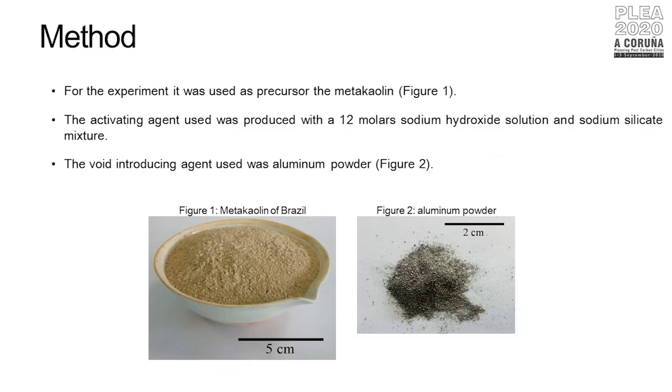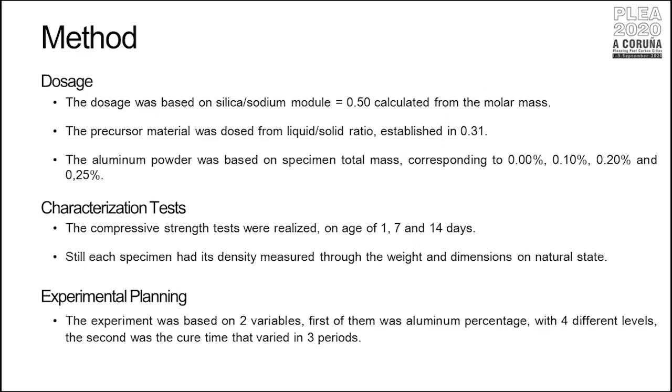For the experiment, metakaolin was used as precursor. The activating agent used was produced with a 12 molar sodium hydroxide solution and sodium silicate mixture. The void introducing agent used was aluminum powder. The dosage was based on the silica to sodium module. This value was 0.50, calculated from the molar mass. The precursor material was dosed from the liquid to solid ratio, established at 0.31.